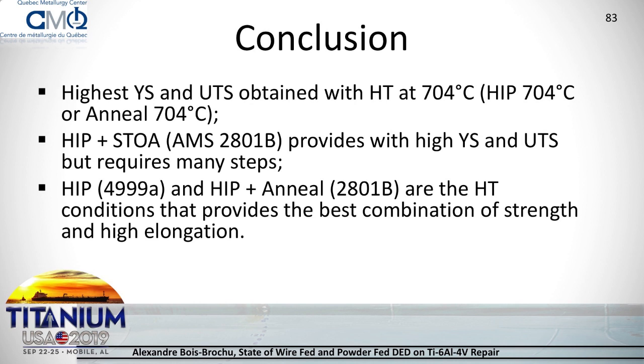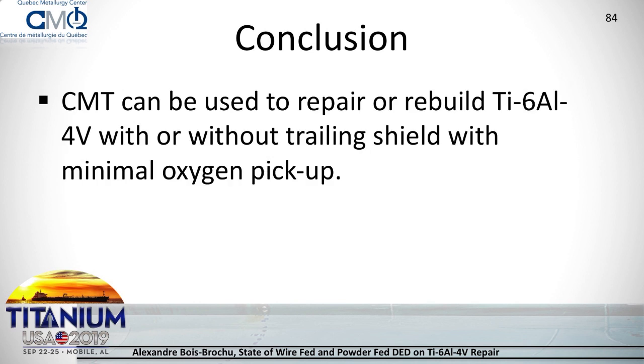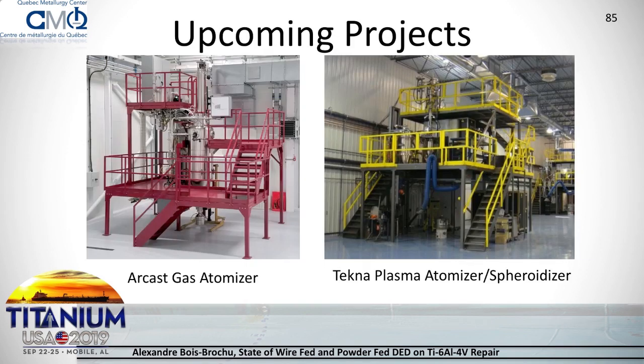And you can do HIP plus STOA with very good mechanical properties, but it's a complex heat treatment that you don't need to use if you have alternatives, such as, finally, only HIP at 900 Celsius or HIP plus anneal at 704. Those are the combinations that provide the best combination of strength and high elongation. And then CMT can be used to repair and rebuild TI-64 with or without a trailing shield with minimal oxygen pickup. So those were the results for the project on TI-64.